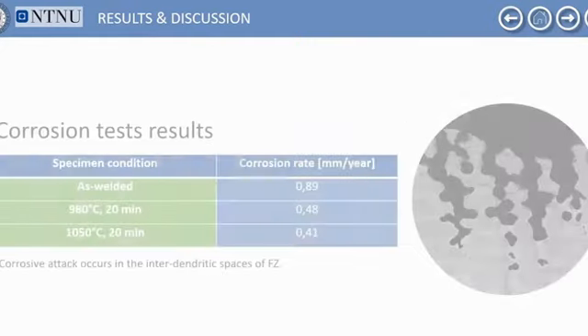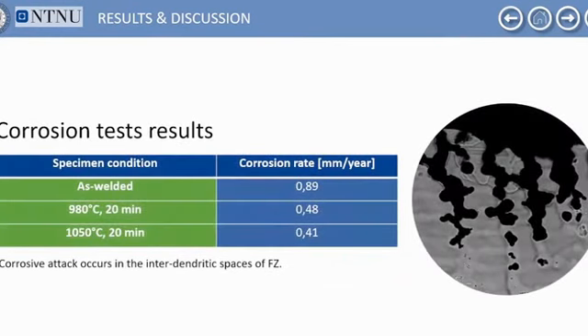So these are the results of corrosion tests. In particular, we can observe that the post-welded heat-treated joints behave better than the as-welded joints. So post-welded heat treatments were effective in order to restore more or less the corrosion resistance of these alloys, and the best results are obtained with the highest temperature, 1050 degrees. We also observe that the corrosion attack occurs in the interdendritic zone of the fusion zone.